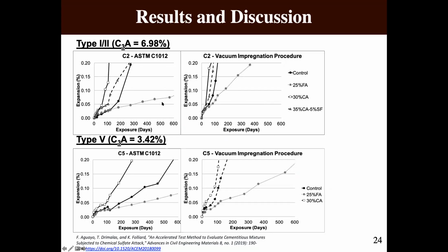Obviously, you should see an improvement of sulfate resistance, just simply because you have a lower aluminate content. This is because the aluminates are primarily attacked when you have sulfate exposure. And then type 5, even lower C3A, having a longer time until reaching, in some cases, up to 600 days, you still have not actually exceeded the 0.1 expansion according to C1012. But when looking at the vacuum impregnation procedure, you have a much more dramatic increase.